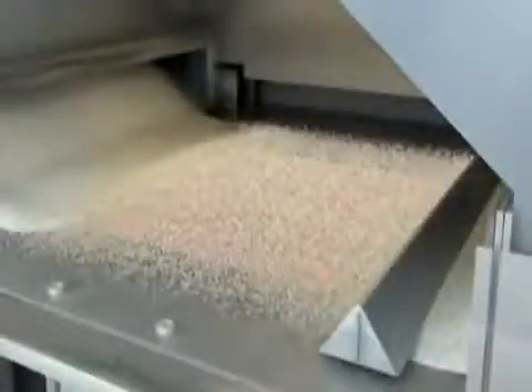We then spread the powder into a thin layer of material and preheat. We then go through and sinter the powder exactly where the CAD file states. We repeat the process over and over again for each layer that we've created in our file, and we build up parts.